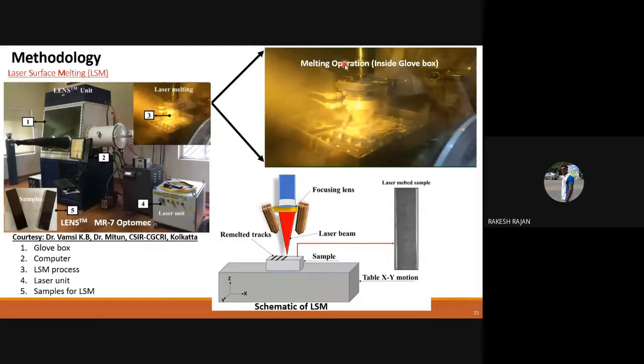So this is the glove box inside that additive manufacturing area, and this is the nozzle. You can see that through the nozzle, the high intensity laser beam is falling on the surface. This is a sample which is fixed on the CNC platform, and this is the surface of the sample after laser melting. You can see the stripes on the surface of the sample. That means that you are not changing the bulk property of the sample. You are just changing a certain depth of modification, keeping in mind that this is for controlling the degradation. So this is how this surface modification of magnesium alloy works.